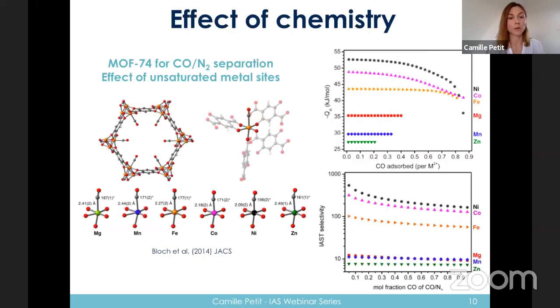It has unsaturated metal sites, which means that those metal sites that you see here can coordinate with some adsorbate, in our case here, CO. And so depending on the metal that you use for your MOF, you will have different strengths of interaction. And you can see that here with the heat of adsorption, that will change depending on the metal that you use. And this is related here to the distance between the metal and the CO molecule. And that can be taken as an advantage for CO-nitrogen separation. You have more examples of how to take advantage of that chemistry in the webinar by Philippe Lerouillet.